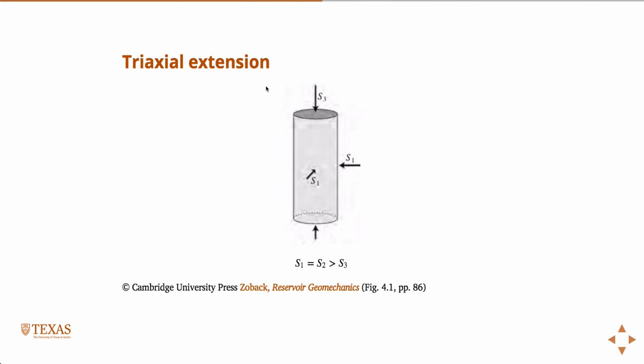So now the sample is in compression. And now we start the real test. And what we do there is we actually release the compression axially. So while we call it extension, it might be called like compressive release. Triaxial compressive release test would probably be a better name for it. So we squeeze the sample until it's under hydrostatic compression. And then we release the load on the end until the sample fails. And so that's a triaxial extension test. Basically, usually any apparatus that can do a hydrostatic compression test can also do this test. So they're also fairly, if you have the equipment, then they're not too much trouble to do.